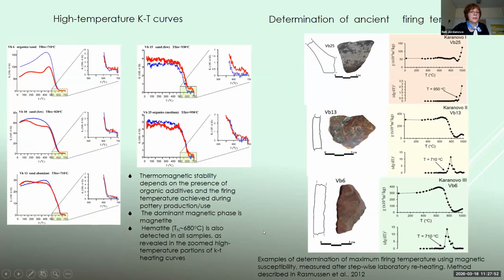We also studied magnetic minerals which are present in the ceramics. Here you can see several examples of high temperature magnetic susceptibility curves. Generally, magnetite type mineral is dominant in the samples, but we also found a small component which is related to hematite presence in almost all samples.